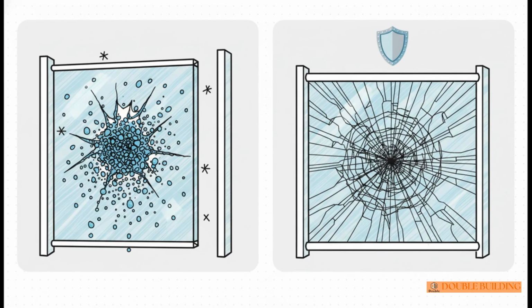Think about this stark reality here. If you take a standard 10mm monolithic fully tempered glass panel, the kind we used to see absolutely everywhere, and it breaks, well, all that stored elastic energy releases at once. It shatters into tiny granules that just fall away in seconds. In an instant, you have zero barrier function. A drop-off is completely exposed.